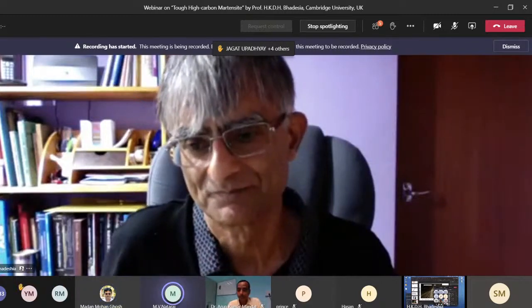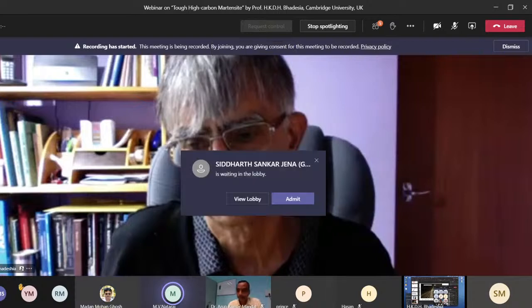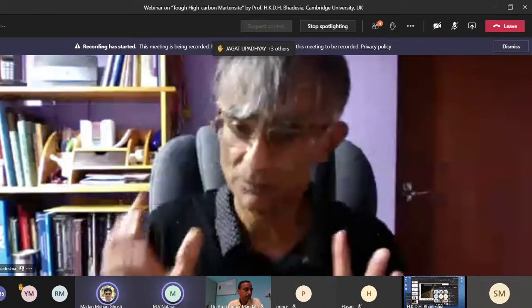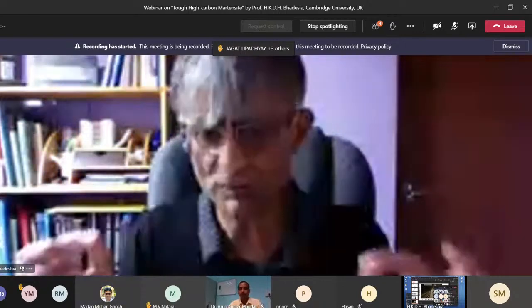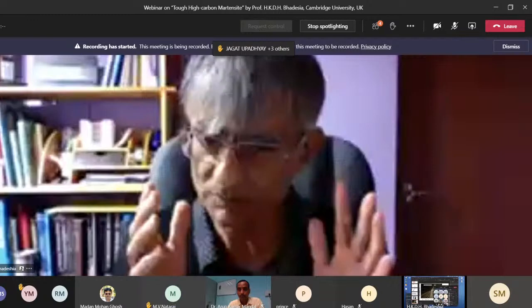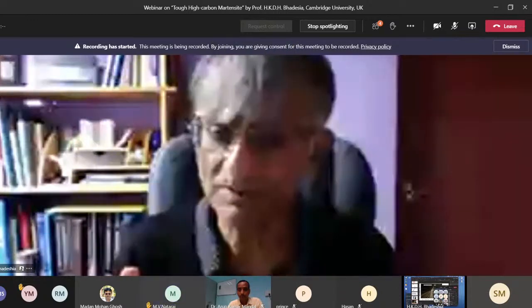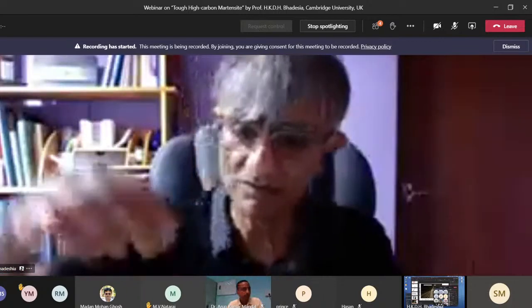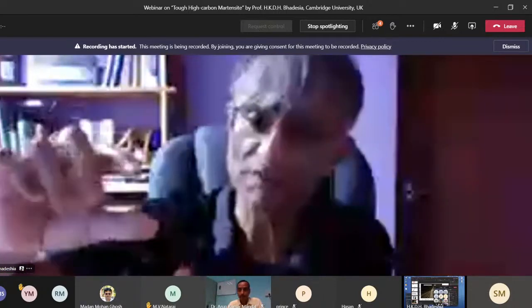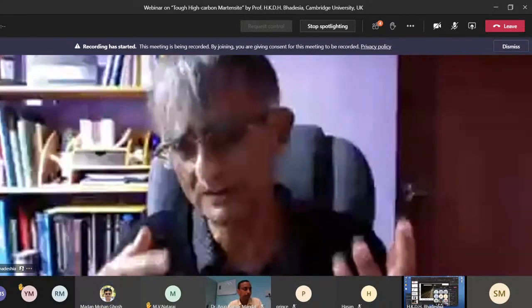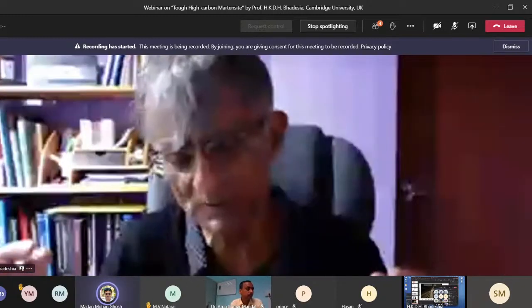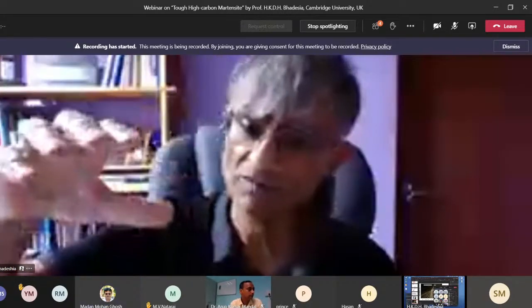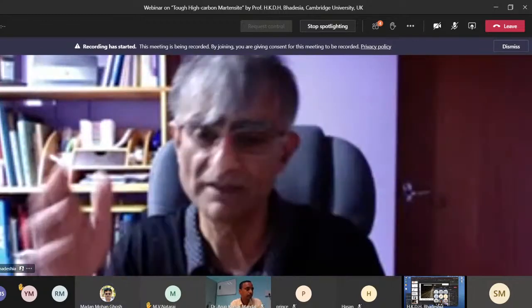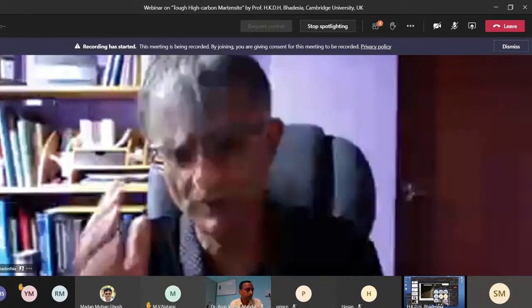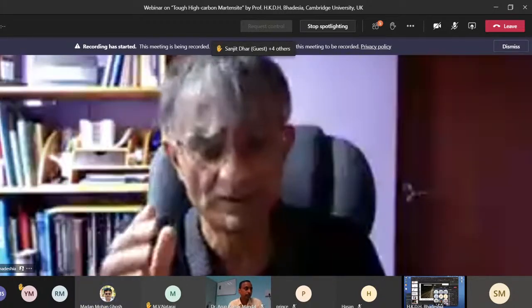Sir, suppose the carbon content is 0.04, is it possible to get the martensite? Yes, in fact, you can get martensite in pure iron. Supposing you take absolutely pure iron, a single crystal, and you cool it at about 10 to the 6 Kelvin per second, it will be martensitic, and you can see the crystal bend according to the shape deformation of martensite. And the shape deformation is what defines it as martensite, and therefore you get a plate shape. Whereas if you cool the same thing somewhat slowly, then you get equiaxed grains of ferrite. So yes, it is absolutely possible to get martensite in 0.04 weight percent carbon steel.